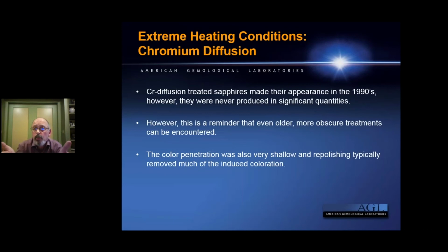I also want to take a moment just to talk about chromium diffusion. This is something that did make its appearance for a very limited time back in the 90s. Then we didn't see it because it's very difficult to diffuse chromium into corundum. Actually, it's a very shallow penetration. The colors are readily polished away when you're having to repolish the stone.